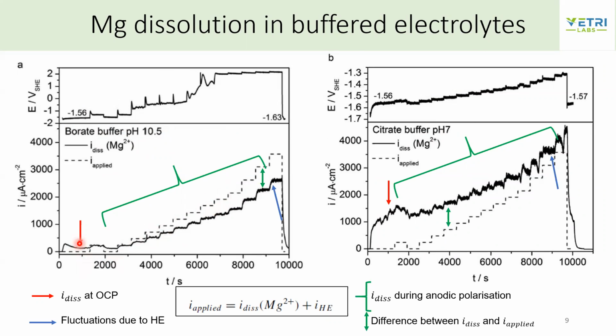What they found when they compared pH 10.5 versus pH 7 is that the OCP current was much higher in the case of pH 7, that is, with relatively lower pH, there was more dissolution. The fluctuations in the current, which they attribute to hydrogen evolution, were significantly higher near neutral pH. They also saw that the difference between the applied current, the dotted line, and the solid line, is much smaller in the case of pH 10.5, whereas it was much higher in the case of citrate buffer of pH 7.